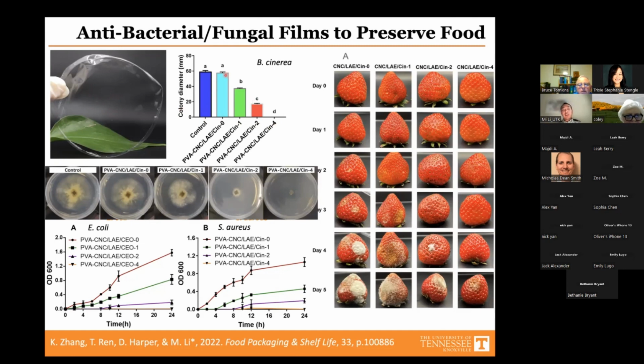film. Then we measured the colony diameters of the fungus, and it turned out that when 1% was added, it had a stronger inhibition, 2% significantly inhibited the growth of the fungus, and 4% completely inhibited it.